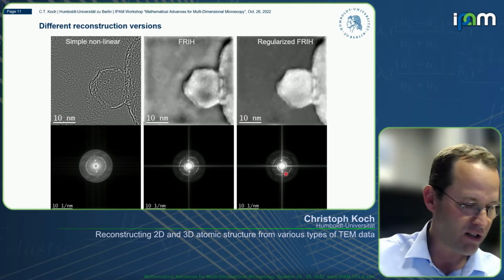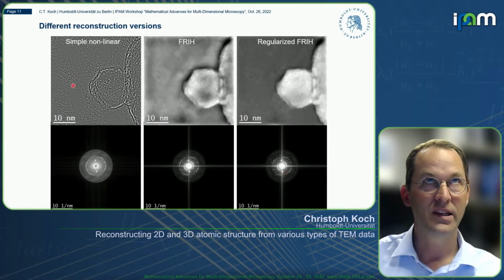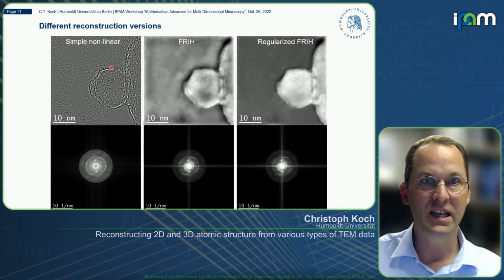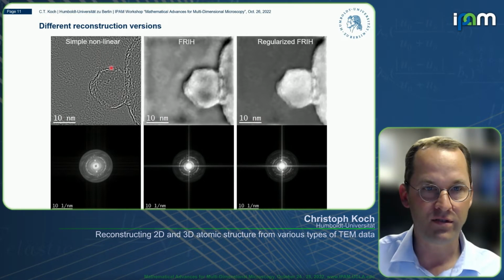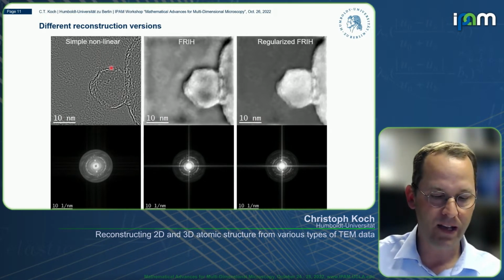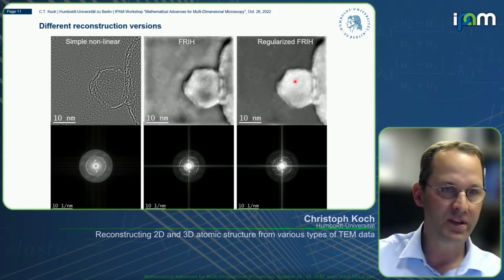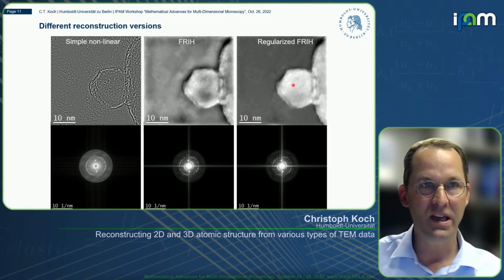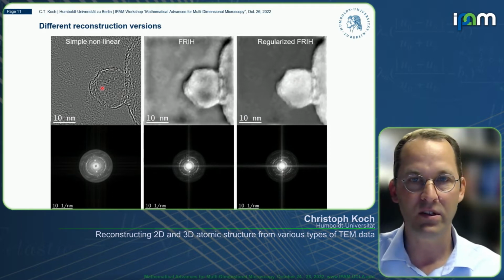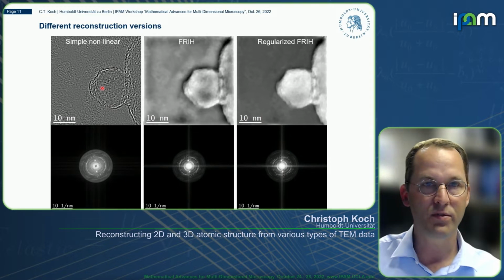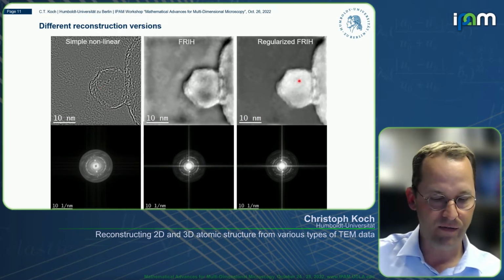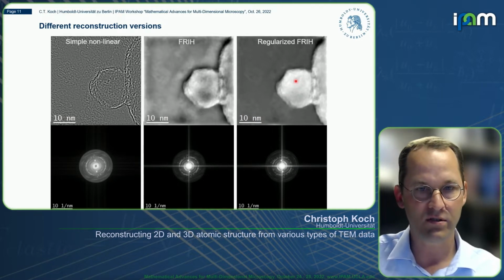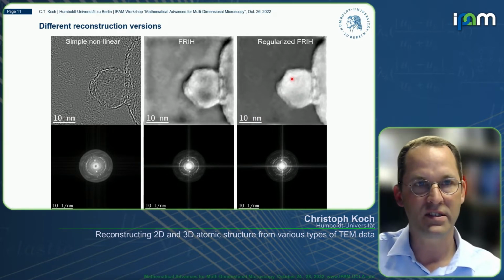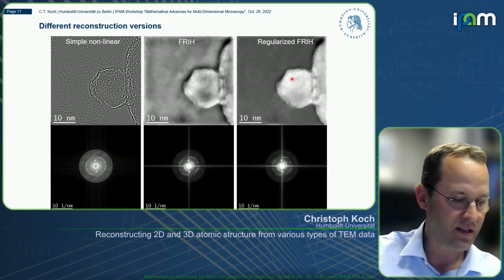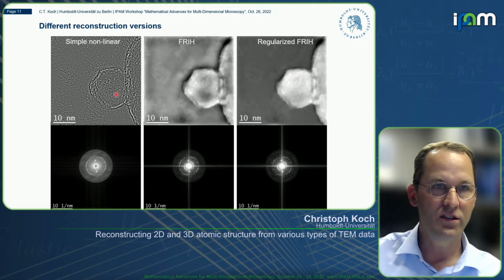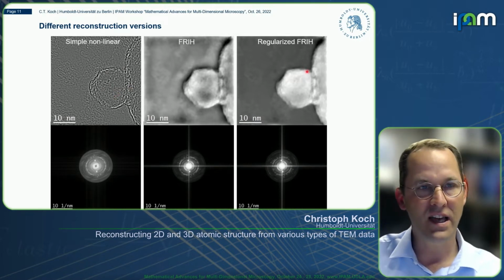So if you look at this reconstruction over here, that may be more easily and directly interpretable, but it's only half the truth. You can take this one here and apply some high-pass filtering to it and get something that looks like this again, if you really want. But you may also be after very different information. For example, you may want to know something about the thickness of your sample, which is proportional to the phase shift that you see here, because the phase shift is proportional to the mean inner potential multiplied by the thickness of the sample. That information is absolutely lost in this case, but it is retrievable here. So once you have this full information, you can still decide what you want to do with it.